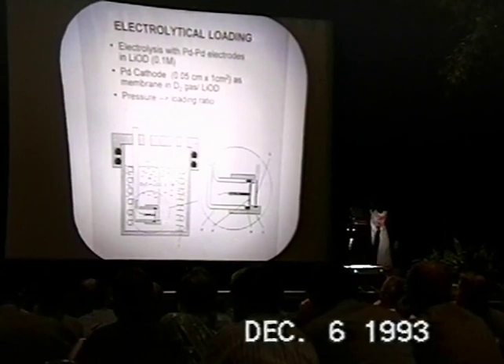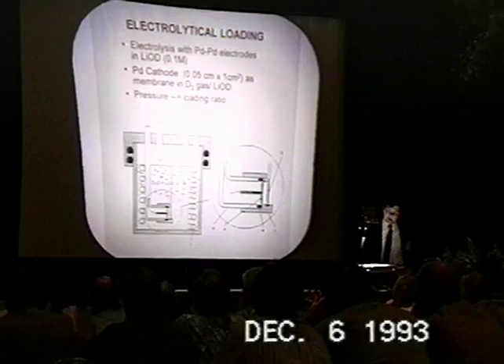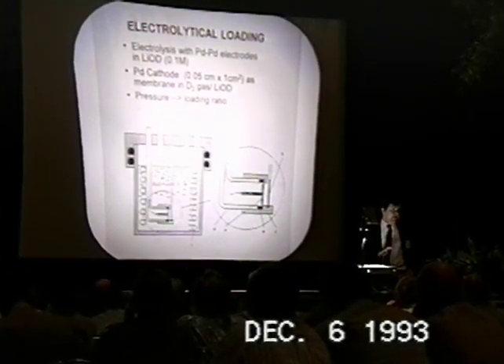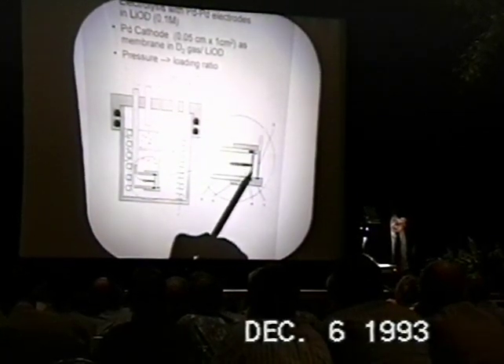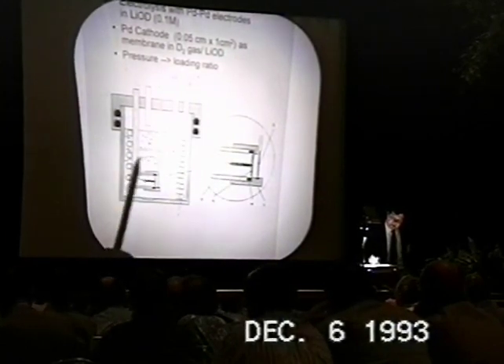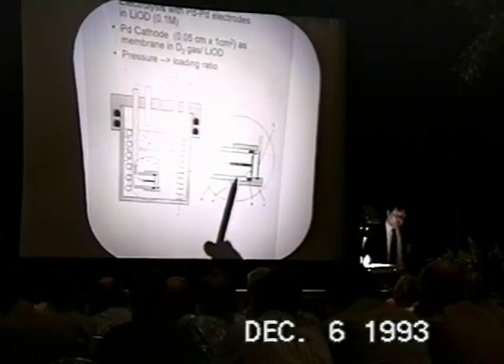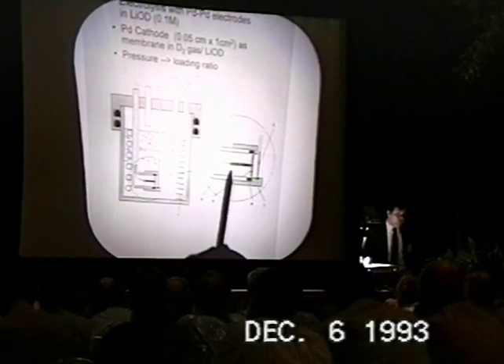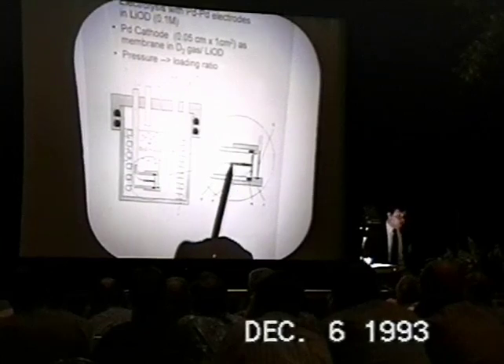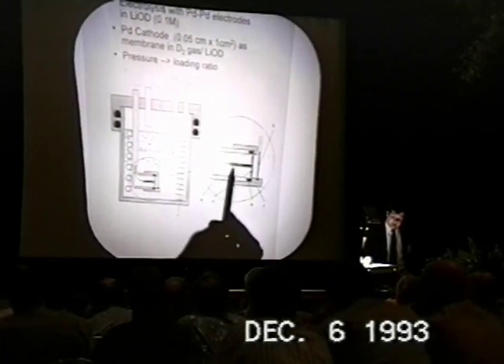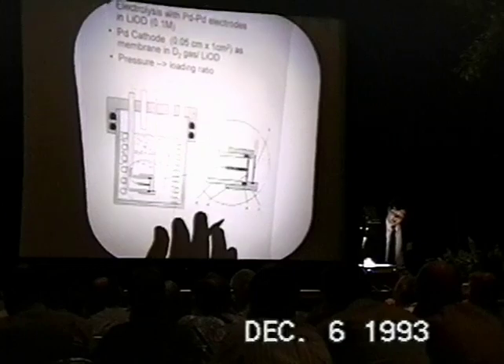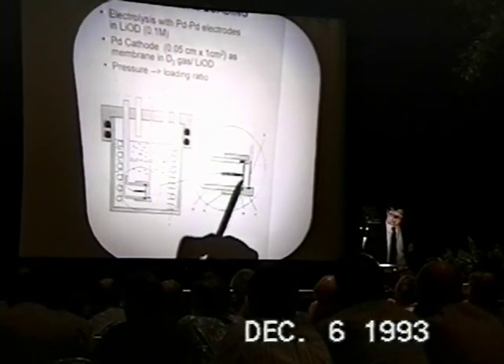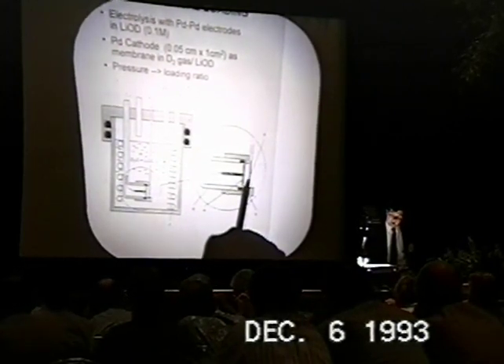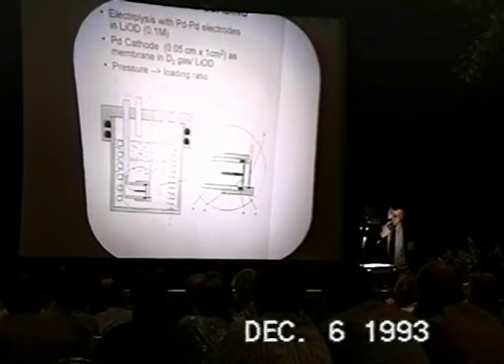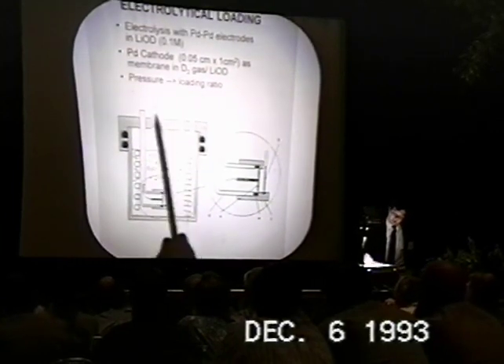The Pd cathode is a particular cathode. It acts as a membrane between a gas and LiOD system. As you can see here, the cathode is supported by a glass pipe which goes inside the cell. Inside the glass pipe, we make vacuum, it's always evacuated, and so we can measure the flux coming out from the backside of the cathode. With the flux measurements, that's the pressure measurement, we can have an idea of the loading ratio at the gas surface cathode. In front of the cathode, we have the anode, which is naturally in the electrolyte, and so we make electrolysis. This is our setup, the cell setup.